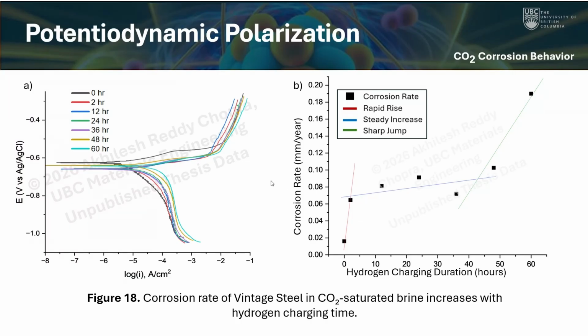Now, there may be two reasons for this. One, of course, is the increased surface area, right? So at 60 hours, the actual surface area of the steel is no longer the same as an uncharged clean surface. Now that we have blisters, we're increasing the surface area, and therefore the current that we generate would also increase in magnitude, right? But I also, what I don't show here, I also performed EIS tests. So these are electrochemical impedance tests, where I wanted to look at the charge transfer resistance of the steel. So basically, it's the willingness of that steel to give up an electron.